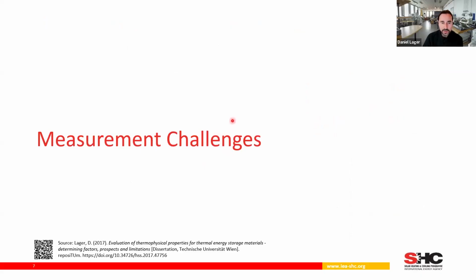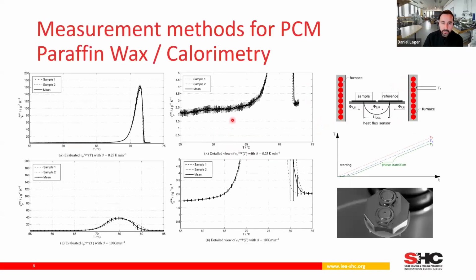So what are now the challenges in the measurements? When you measure these materials, you want to know, for example, the specific heat capacity or the phase change enthalpy. And for this, there is a typical methodology called calorimetry. In that case, differential scanning calorimetry, which is shown here on the picture on the right side. So you have a sample, you have a reference, and then you heat up both and you measure the temperature difference between these two. And this signal you get out of that, you see here on the left pictures.